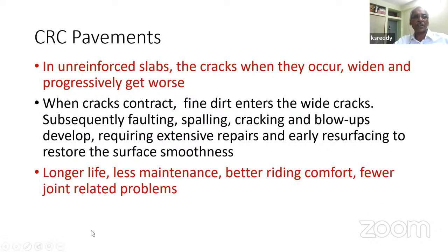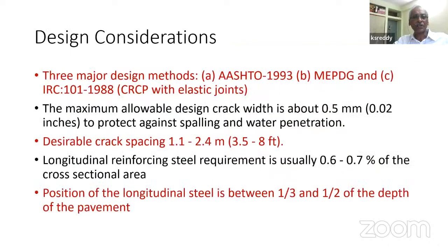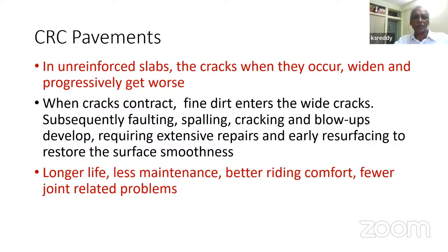So what is the design philosophy here? We have reinforcement here, you got slab there, and you are going to expect cracks to be forming, and they may be of different width, different spacing. So what we design these slabs for is to ensure that the crack spacing is controlled and the crack opening is controlled. We don't want it to be opening up too large. We don't want the crack spacing to be too small or too large. Both cases you will have a problem. Okay, I'll show what it is.